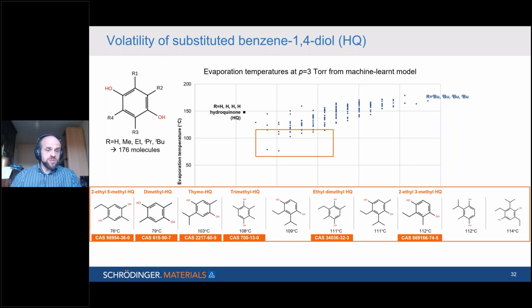You can see at 76 degrees C, there's 2-ethyl 5-methyl hydroquinone. Close to that at 79 degrees C, dimethyl hydroquinone. And then a thymohydroquinone at 103 degrees C. And the list goes on, really quite a diverse range of molecules. Some of them are commercially available, as I've indicated there with their CAS numbers, and they have substantially better volatility than the parent molecule hydroquinone. So rather counterintuitively, in this case, adding heavier R groups actually improves the volatility. And I think this is probably down to entropy and removing some of the symmetry of the system and making it easier to form a vapor in that way.